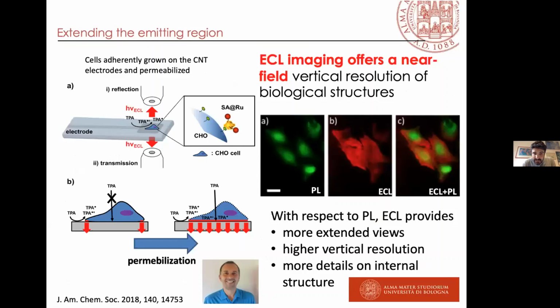After that, Neso Sojic had this nice idea to use a permeabilization approach, to permeabilize the cell's membrane and allow the TPA to reach the electrode also under the cell membrane. In this way, we can have a real map of the first few micrometers of the cells, we can avoid these holes in the cell visualization, and we can have homogeneous ECL emission, which is the emission only of the basal plane of the cells. This is very similar to what is called near field microscopy, with a vertical resolution of around 1 or 2 micrometers up from the electrode surface. So you can have a vertical resolution from the electrode surface towards the bulk of the solution.